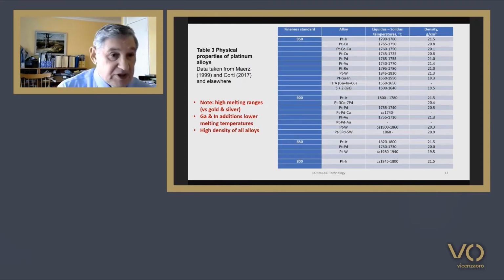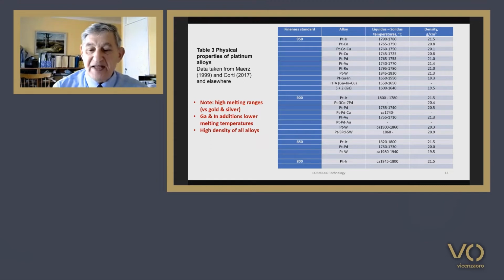This table, table 3, shows the higher melting ranges and densities of platinum alloys. And we can note that gallium and indium additions, as we can see there, there's 3 alloys at the bottom of the 950 section, have lower melting temperatures compared to the other platinum alloys. And we note also the high density of all the alloys.